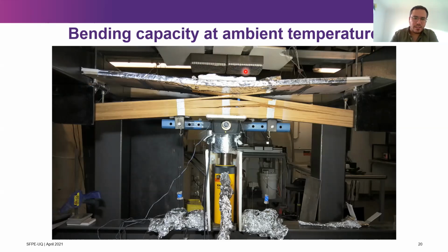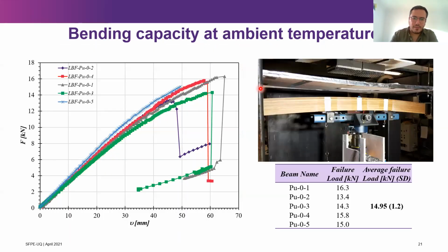So what you see here is a radiant panel. These gypsum boards were protecting the other part of the beam that we didn't want to expose to a fire. And again, from the results of this test at ambient temperature, we basically obtain our failure loads in bending under that particular configuration. And obviously we understood the force deflection curves.